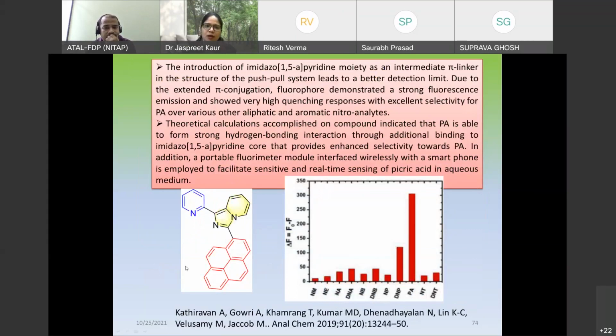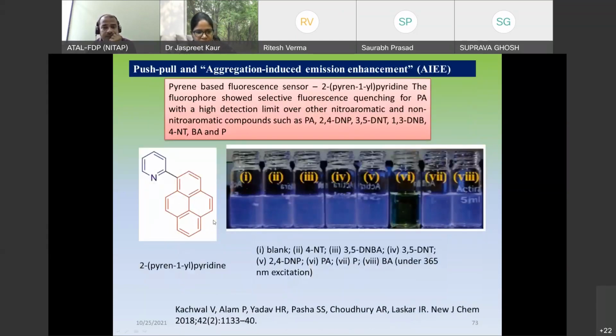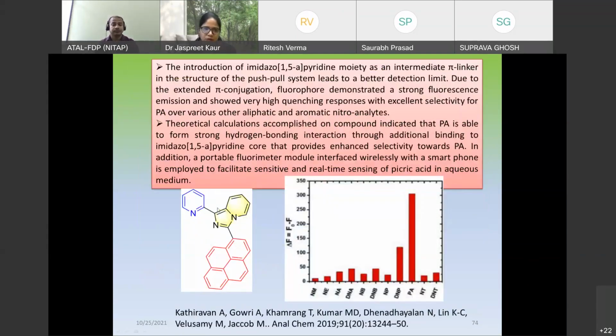Next one is the imidazole moiety. When the imidazole moiety is attached over here, you can see this is our imidazole moiety. So this is the linker. The pi linker is imidazole, and in the previous case there was no linker over here. So now this group, Jacob, they have introduced the pyridine system and an intermediate pi linker is added over here. The imidazole group is attached over here and they show extended pi conjugation, and that is why they show high quenching response and better selectivity for picric acid out of the various types of nitroaromatic compounds.